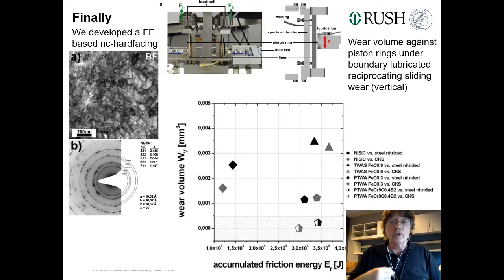What was my personal problem with that project? So we measured the wear volume in the laboratory at 80 degrees C in order to mimic this boundary contact without additional soot particles. So this is the wear volume plotted over the accumulated frictional energy. Again, both cannot be directly related. This is the Nikasil stuff, which is not used anymore because the nickel nanoparticles are not too healthy for anybody who would breathe them. This is the stuff that the industry used, and of which they thought it should have a smaller wear rate. So this wear rate was too good. Here the wear rate, they would say, yeah, it was not too bad, but the friction was quite low.